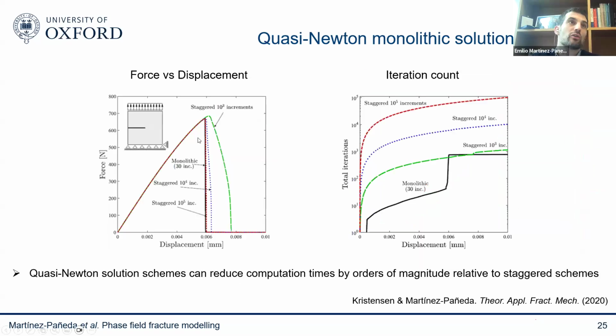And the beauty of this quasi-Newton method is that when you compare to the single pass stagger approaches, you can see that in order to reproduce the right force displacement response, the stagger approaches need to use many increments because you have some sort of semi-implicit method. But you can capture the right result with very few increments with this monolithic approach. And when you compare the total number of iterations, you see that you can reduce the total number of iterations by orders of magnitude. So this BFGS quasi-Newton approach, I think, is quite powerful.